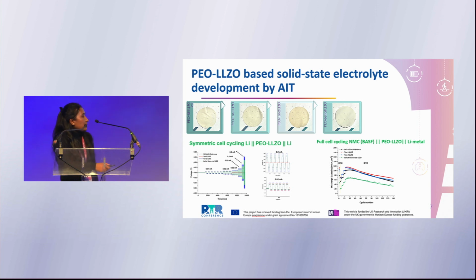And in the final one, first we did the formation cycling at very low current, C/30, and then we went for C/10. And here you can see all the materials reached the cutoff voltage of 4.2, which is the voltage window of the NMC. And at around C/10 we had very stable cycling for almost all the LLZO particles prepared. And interestingly, the LLZO particles prepared in the project show really good performance compared to even the commercial LLZO reference material. So we are still confident that these fillers can go forward for the further development of polymer electrolytes to achieve the end goal of this project.